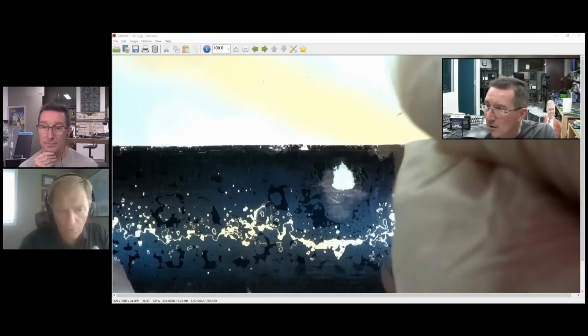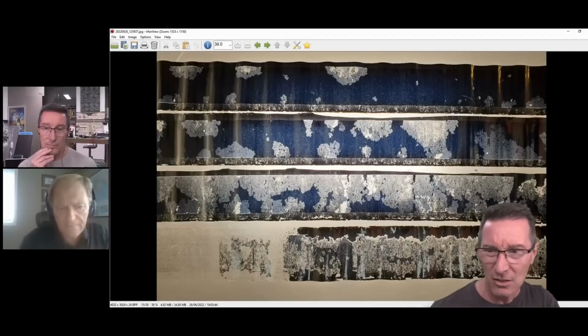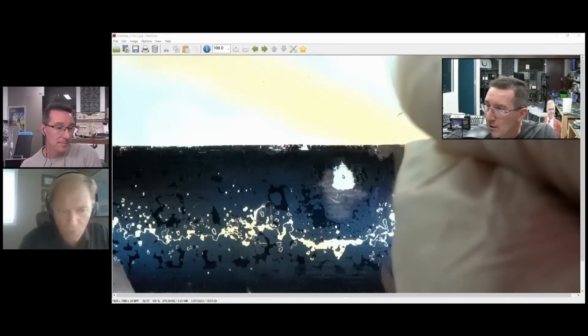Of course, those small holes, or maybe the big hole that you have up on the upper right there, that's a result of actually self-healing. So that's the vaporization, as you'd expect. Now, when we start getting into the other area, we could explain things kind of easily. As you roll this thing out from left to right or right to left, you've noticed that there's a variance. Some of that variance is due to the difference in the connectivity from the schoopage on the termination to the actual electrode. At one point in the video, you showed a very light background with some speckled scenarios, and that was just moisture in a high resistance scenario. But what we're seeing here is in the crack lines, the lightning bolt looking thing. Yeah, that almost went through the whole thing.